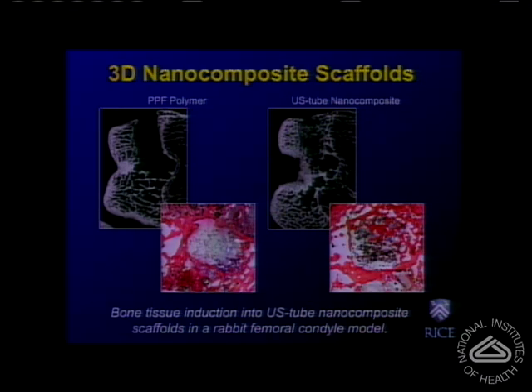The objective of the study was to assess the biocompatibility, or the tissue response, to the implantation of the material. And here we have the case of the polymer alone that was implanted in the femoral condyle of a rabbit model. And what we found in the case of a porous polymer is an excellent response that involved apposition of bone tissue at the perimeter of the biomaterial, as shown here in the micro-CT image and also shown here in the histological section, where the biomaterial is in the center and what is stained as red is a trabecular structure of the surrounding bone.